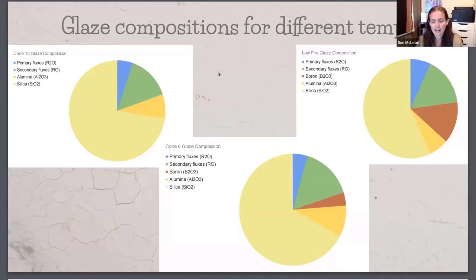So as far as temperature goes, here's an example of a cone 10 glaze where we've got glass formers, silica and alumina, and then we've got fluxes. That's similar to the pie I was showing you earlier, way more glass former than flux. And cone 10 glazes don't require boron to melt at that temperature. Once we move to cone 6, now this orange section, that's the boron.